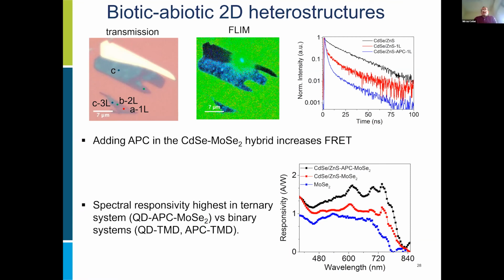So it matters in this kind as well, the ability to do these ultrafast measurements, but now more and more it matters for 2D heterostructures. Like the last examples I showed, those processes are extremely fast, like picosecond time scale. And the transient emission somehow gives up at extremely fast time scale. So that was one of the reasons we had to develop transient absorption methods, which are pump-probe-based methods, so we can go into the picosecond time scale to access processes like electron cooling, or sometimes charge transfer can be extremely fast. So those are extremely useful tools.